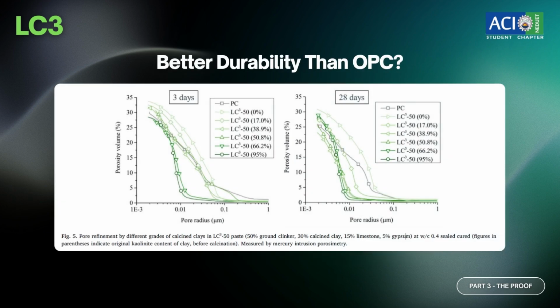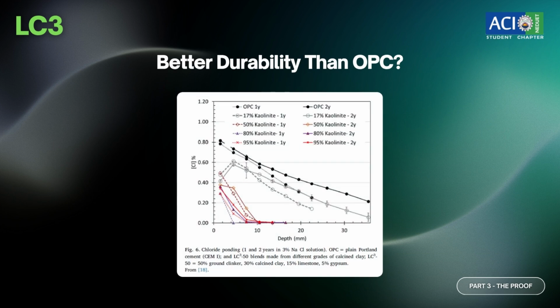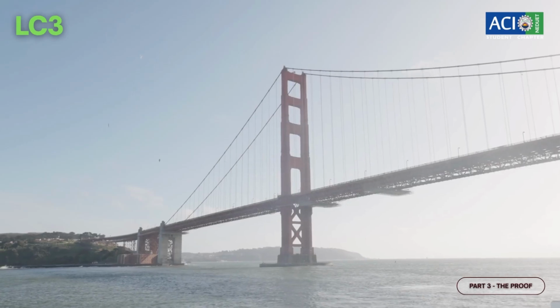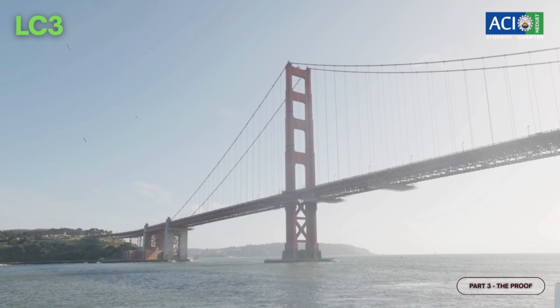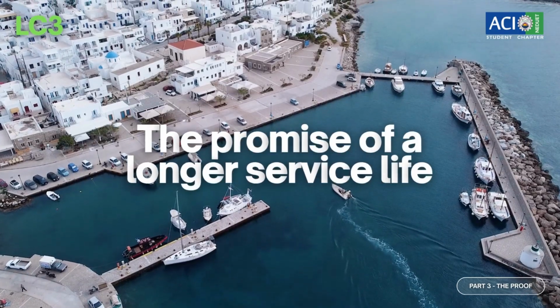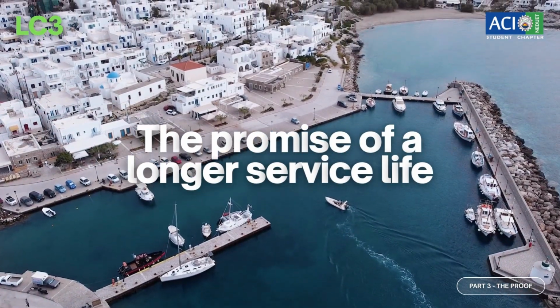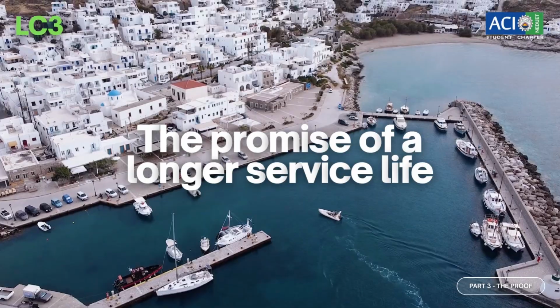In some aspects, it performs even better. LC3 shows a highly refined pore structure and excellent resistance to chloride penetration, which is a major durability concern in reinforced concrete. In fact, studies have reported chloride diffusion coefficients for LC3-50 to be about 10 times lower than those of plain Portland cement. For bridges, coastal infrastructure, and other exposed structures, that can translate directly into longer service life and better protection of reinforcement.